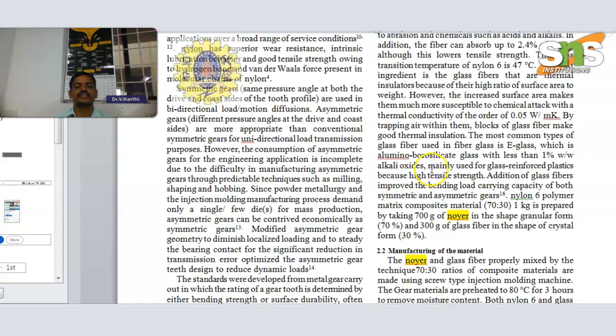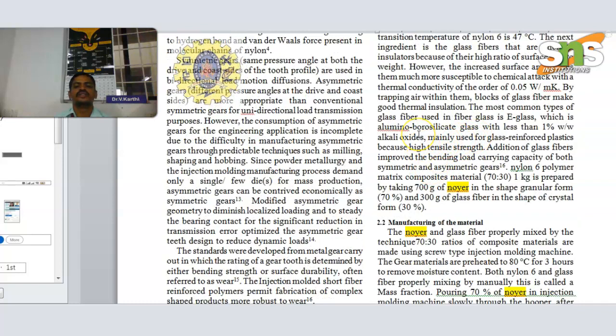The E-glass, which is aluminum borosilicate glass with less than 1% alkali oxide, is mainly used for glass reinforced plastics because of its high tensile strength. Addition of glass fiber improved the bending and load carrying capacities of both symmetric and asymmetric gears.